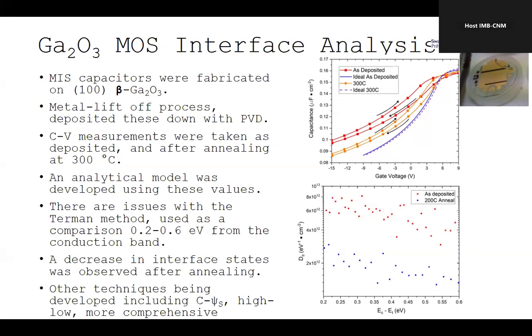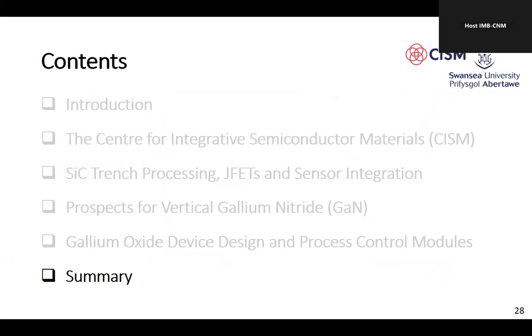So we looked at, there's some processing details here, but what we found was that after some CV analysis as deposited, we can do a post-deposition treatment at 300 degrees C, and we get a lot less hysteresis. So we can remove the impurities from an aluminium oxide layer. The dielectric was aluminium oxide. Furthermore, using high-low CV techniques, we found that we reduced the interface trap density considerably after this post-treatment as well, by extracting the interface traps from the CV characteristics.